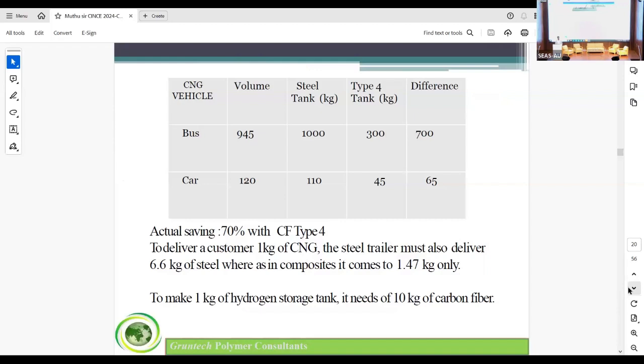In a bus or car, a steel tank weighs 1000 kg while Type 4 is 300 kg. You can see the difference, actually about 70% lighter with carbon fiber Type 4 cylinders. Some people use helical winding with carbon fiber and circumferential winding with glass fiber, then the weight goes up, so you should not compare that data with this data. I'm talking about a carbon fiber tank here, not a glass fiber tank. To deliver a customer 1 kg of CNG, the steel trailer must also carry 6.6 kg of steel, whereas with composite it comes to only 1.47 kg.